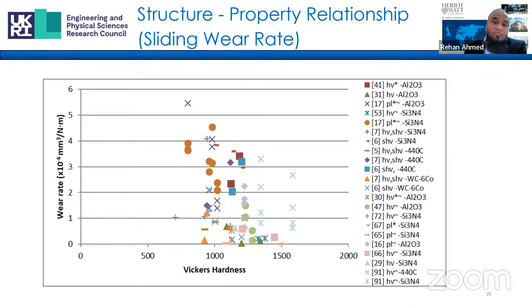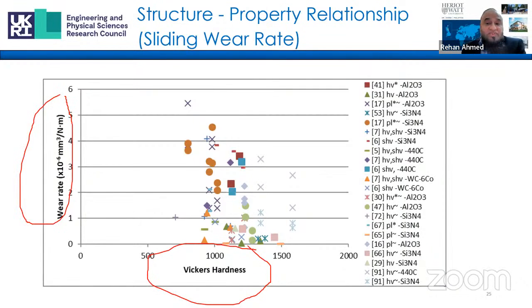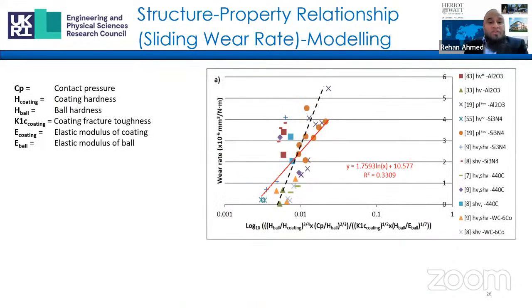So in terms of the semi-empirical modeling of wear rate, there is no generic relationship between hardness and the wear rate. And we can extend this analysis to say, okay, ratio of the ball to coating hardness to wear rate, or the contact pressure to wear rate. None of them actually have any correlation. And this is because of the complexity of the sliding wear process in thermally sprayed tungsten carbide cobalt coatings. However, once we include all the factors such as the contact pressure, the coating hardness, the ball hardness, the fracture toughness of the coating, the elastic modulus of the coating, and the ball material, we begin to see some trends. However, the trend is still not well defined.